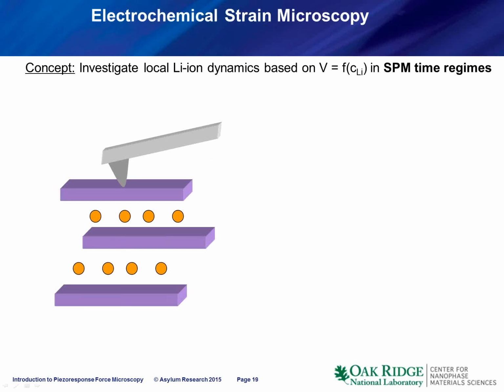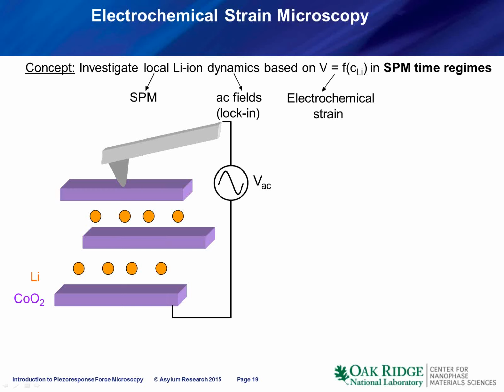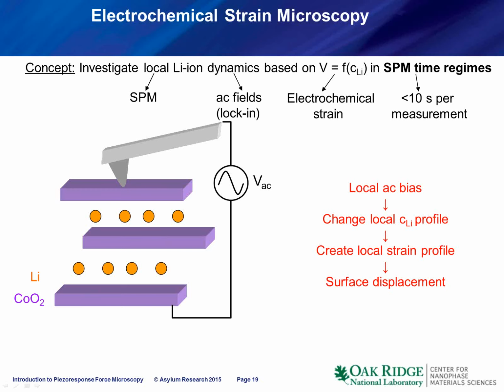The principle of electrochemical strain microscopy is illustrated on this slide. So all we do in this case is put our tip in contact with the surface, same as PFM. We apply bias, and in electrochemically active materials, ions start moving and respond to the electric bias. They kind of have to, because if they don't move, then batteries and fuel cells will stop working. What is remarkable is that in all these materials, the molar volume, or for simplicity, the volume of material, depends very sensitively on the local concentration of mobile ions. So if the ions move, they will cause the material to locally expand and contract.